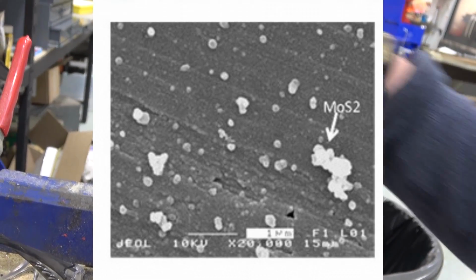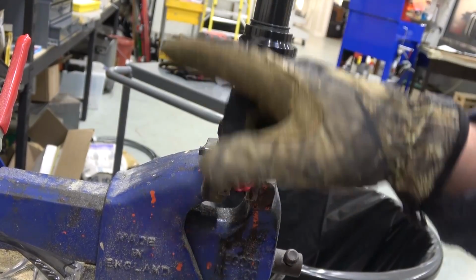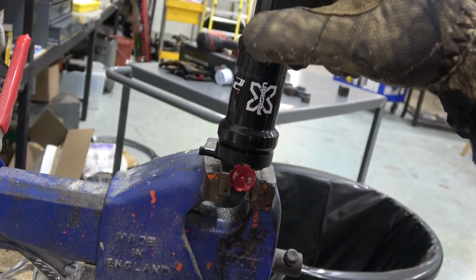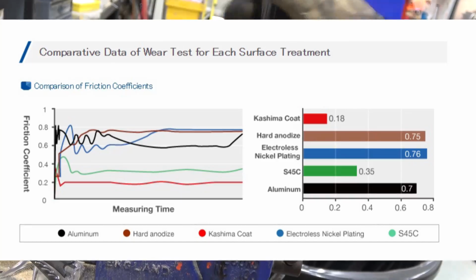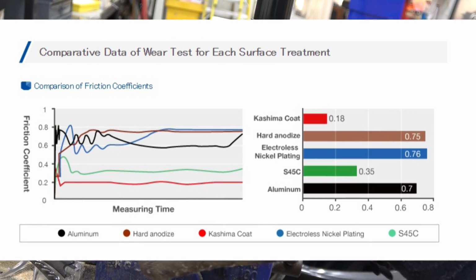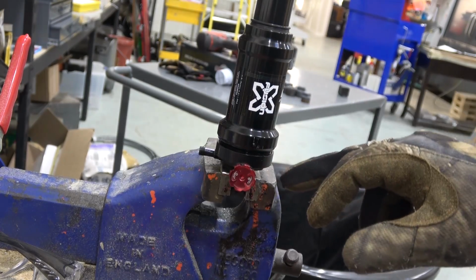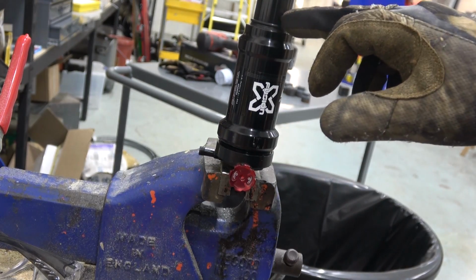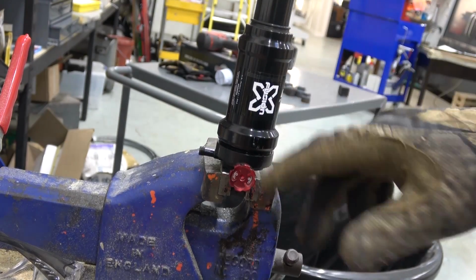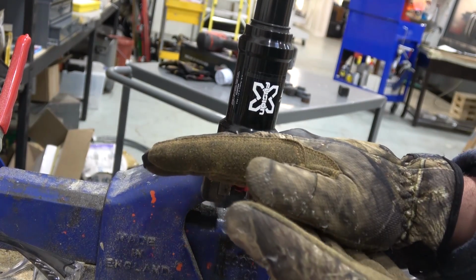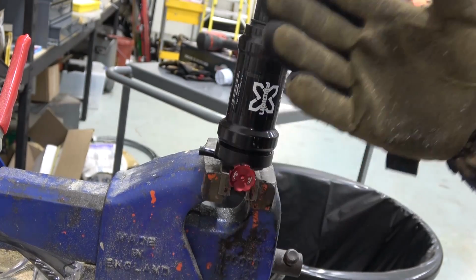In the patent itself here, now I'm getting into it. In the patent itself, it shows some very, very coarse granularity on friction coefficients. But you'll notice they're missing a lot of data there. It's not very scientitious. And what you see is that for dry metal on metal contact, yes, it is quite lubricitous, but the thing is, we always put a little bit of grease on here because you don't want dry friction, dry sliding friction. What you actually want is hydrodynamic slip.